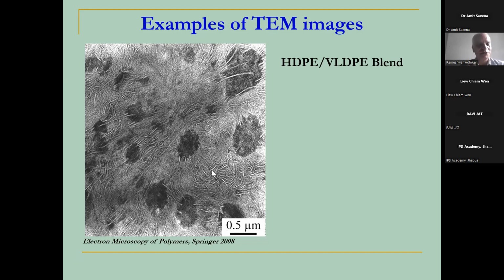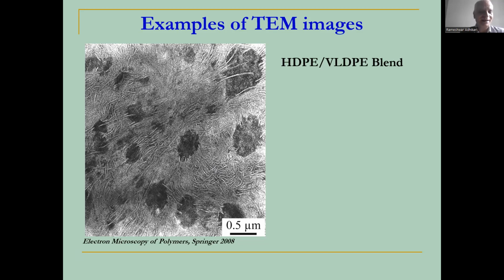The brightest areas are those which don't allow the staining agent to go into them, and those are the crystals. And those areas, for example here, which appear relatively brighter, but not as bright as these layered structures, so-called lamella, are the amorphous region, which allows a part of the staining agent to go through it. Therefore, you can see that the darkest areas are very low density polyethylene. The brighter areas are high density polyethylene. The brightest layers, which are also even going into the very low density areas, are high density polyethylene crystals, so-called lamella. And the rest are the high density polyethylene amorphous regions.